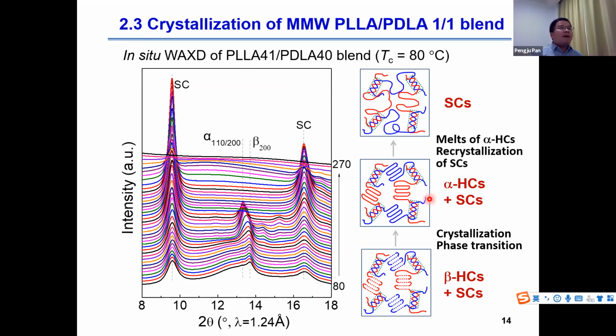Since beta form is a more stable form of homocrystalline structure, we investigate its phase transition during the heating process. We first crystallize the sample at a low crystallization temperature to get the beta form crystal, and then measure the in situ WAXD pattern in the heating process. We first observe the further crystallization of beta form